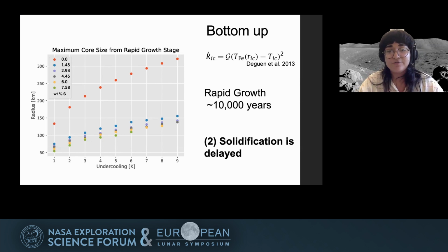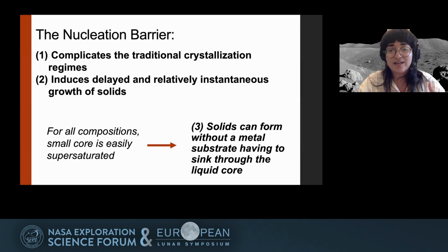We're also thinking about how for top-down plentiful nucleation sites, which I was originally skeptical of because of the likeliness of the presence of a solid layer at the CMB on the moon, we found that the mass fraction of these layers are so small, imagine a sponge 90% water, that once it sank, it would compact to a solid core, but while it's at the CMB, where it's not compacted, there's the question of how big could that extremely porous iron layer be without being detected with new seismic data? And there is the piece of how the Lunar Geophysical Network could help us rule out some of the various models we're offering.